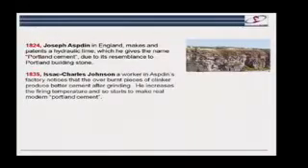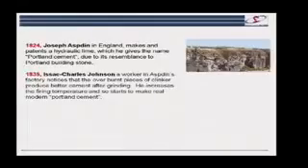And he said, I'm going to call my cement Portland cement because it looks as beautiful as this Portland building stone. But in fact, it wasn't until about 10 years later that one of the workers in his factory realized that the really good stuff was the stuff that was overburnt, that had gone up to higher temperature, and it was really his discovery that led to what's really modern Portland cement.